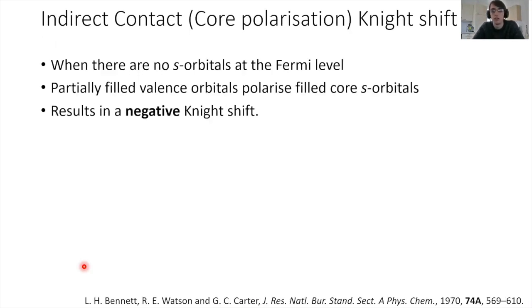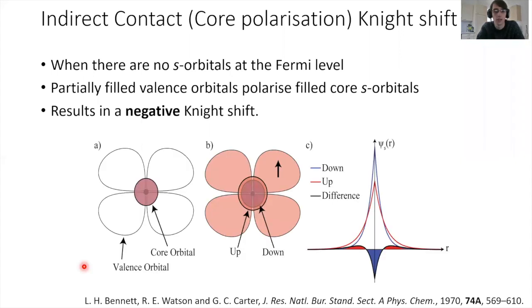But what if we don't have any s orbitals at the Fermi level? Turns out we can still get an effect, and we get an effect by polarizing core s orbitals. And so this is known as core polarization or indirect contact Knight shift. And this actually results in a negative Knight shift. We'll see why that is. So what I'm showing here is a core filled s orbital, and there's an up spin orbital and a down spin orbital, but in the absence of any other effects, these have the same spatial dependence, they're coincident.